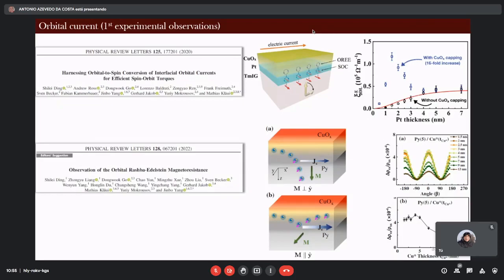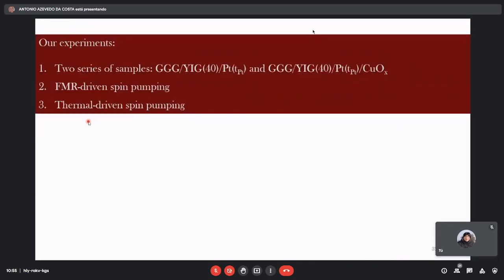So now let me move to the results that we have just submitted for publication. Our experiment was performed using 2 series of samples. One is just yttrium iron garnet, 40 nanometers thick. On top of it were deposited several layers of platinum, varying the thickness. And the other series of samples is exactly this one here, but on top of the platinum, we deposit copper oxide.